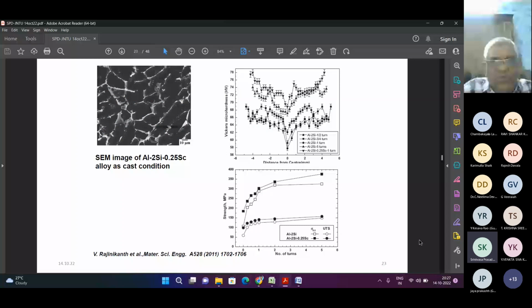So when you are doing high pressure torsion on aluminum 2 silicon 0.25 scandium alloy, in as cast condition, you can see the grain size. I am talking about the as cast condition, not the processed condition. It shows an average grain size of 25 to 30 microns. You can see that due to scandium additions, the refinement has also taken place. This is the actual